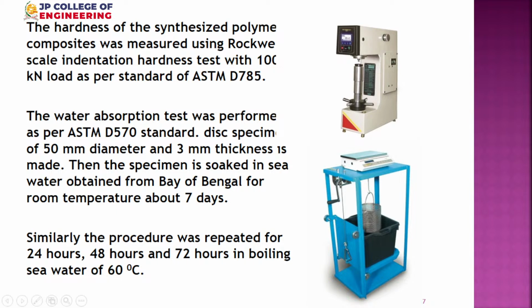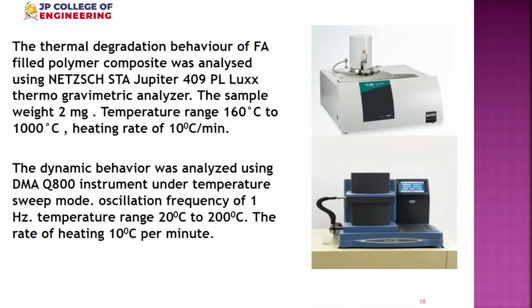The bottom picture shows water absorption testing at normal temperature, as well as accelerated, at elevated temperature. We also thought about not only pure water: in sea coast regions, even the moisture contains salt particles. Therefore we conducted the hygrothermal test. That is, even in boiling water, how much water is absorbed, and at room temperature, how much water is absorbed. That water is salty, taken from the sea itself. So the hygrothermal test is conducted in the bottom setup. Next slide, please.